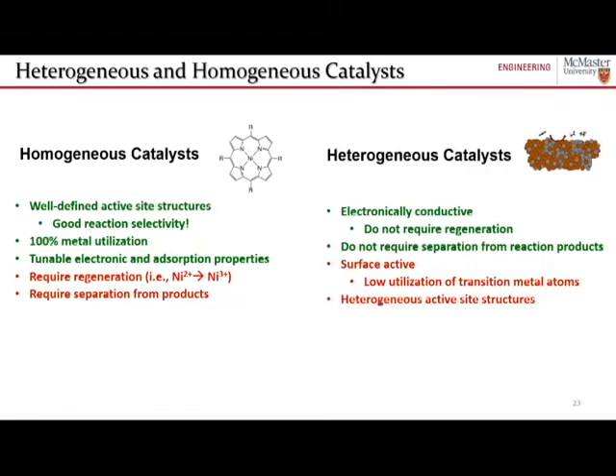But they do have a few challenges. So one is that they're surface active, so there's a low utilization of the transition metal catalyst atoms that you're putting in there, just because the bulk is not accessible to the reactants, so it's not active in the process, as well as the fact that they have heterogeneous active site structures.